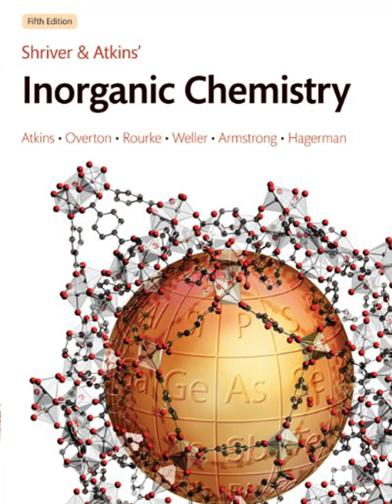Exactly. And then there's mass spectrometry, which measures the mass-to-charge ratio of ions. It gives you the molecular mass, characteristic fragmentation patterns, and even isotopic information, like seeing the distinct pattern for bromine isotopes in a molecule containing bromine. Identifying the pieces. Yeah. And elemental analysis. Crucial for confirming composition. Classic CHN analysis for organic content, or techniques like X-ray fluorescence, XRF, for a broader range of elements. Thermal analysis, TGA, DSC, watches how materials change upon heating: decomposition, phase transitions. And magnetometry directly measures magnetic susceptibility to determine the number of unpaired electrons. An amazing array of tools to probe the inorganic world.